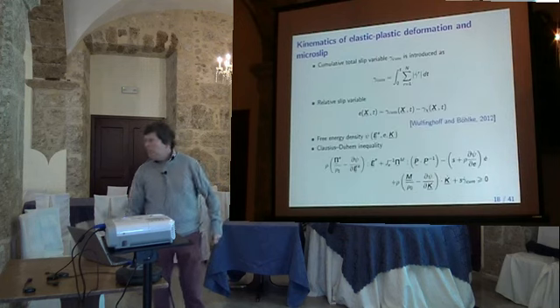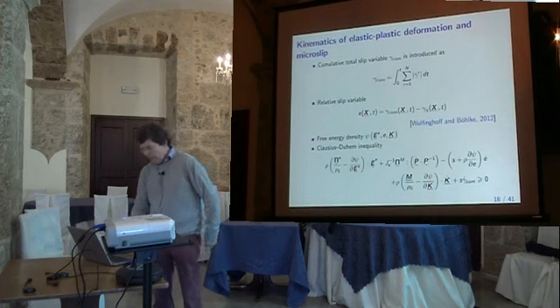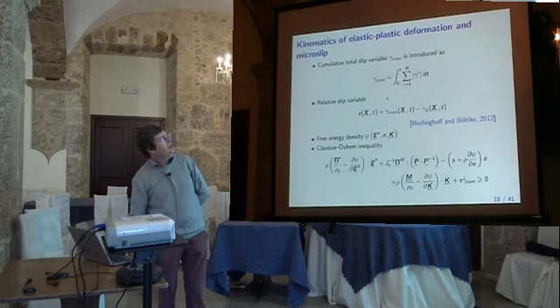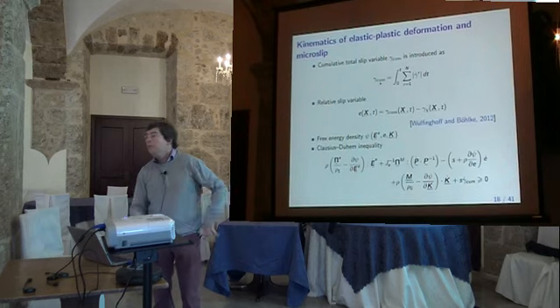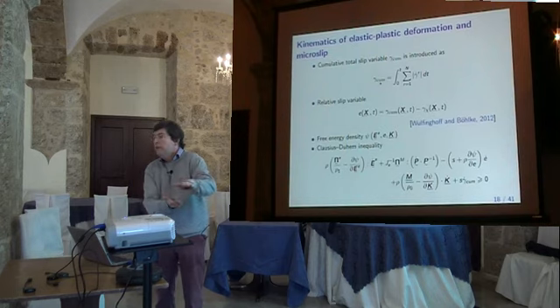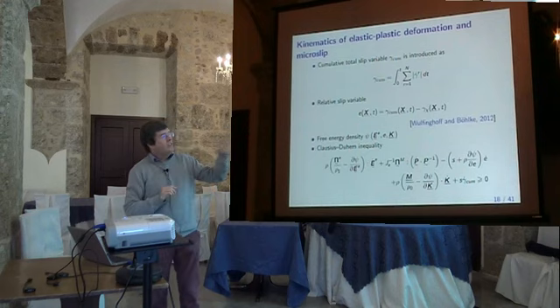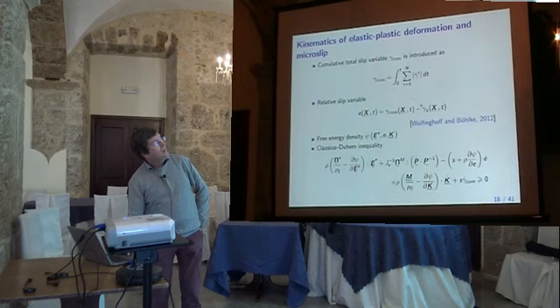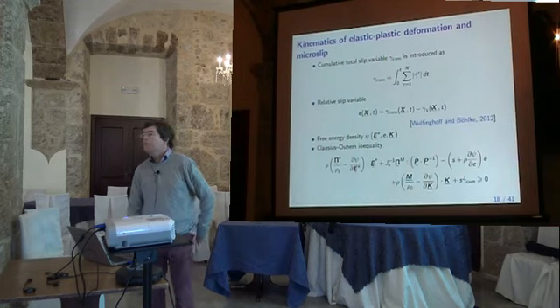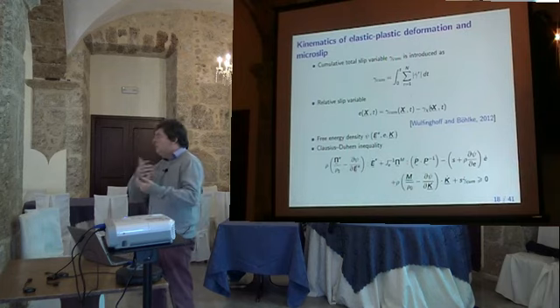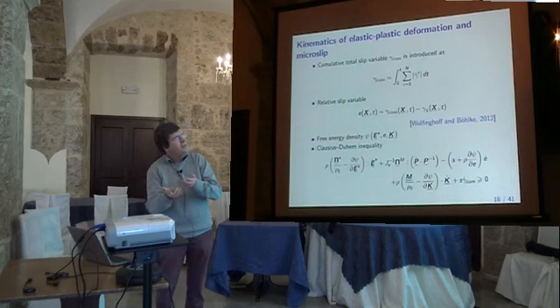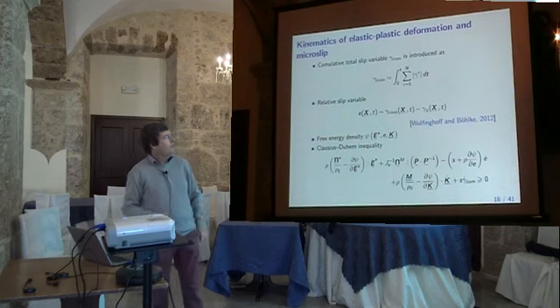Now I have to say what is the chi I considered. So I will take here the slip, plastic slip. So there is only N equal to 1, so it's easy. I take the cumulative slip, so the cumulative shear on the slip plane. This is an internal variable. And I will consider that chi here is a microslip variable. In the same way as before you had a sort of plastic strain, here this is plastic slip simply. More crystallographic if you want.